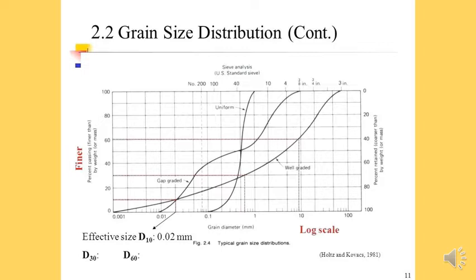So here's another example. We can see here 3 different aggregates. One is gap graded, one is poorly graded or uniformly graded, and one is well graded. So let's look at the well graded initially. Now the well graded, if we were to learn anything about this, we would say that 60% of the aggregate is smaller than 10 millimeters. We would also be able to say 30% of the aggregate is smaller than about 0.6 millimeters. So 30% in mass we're talking about here.